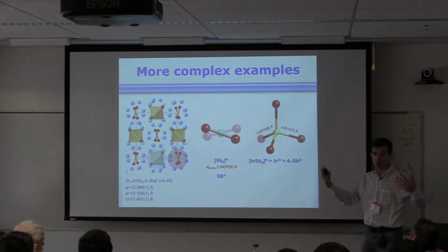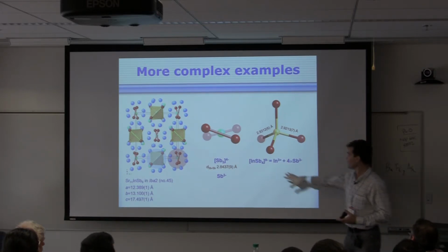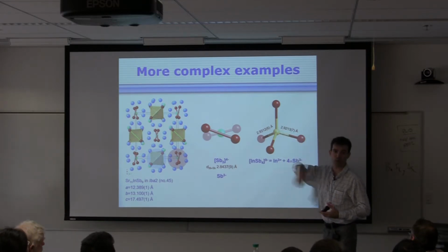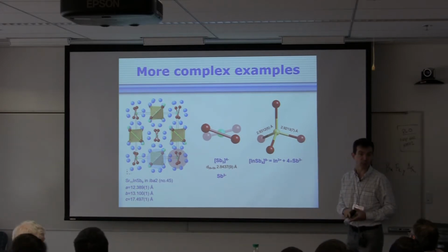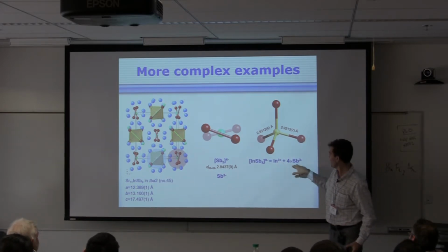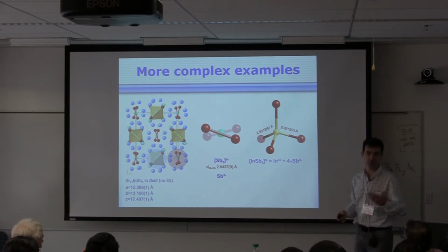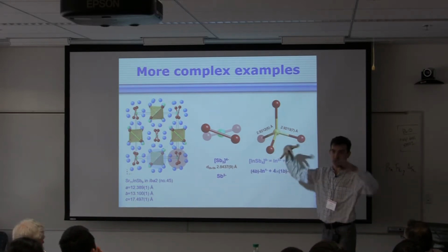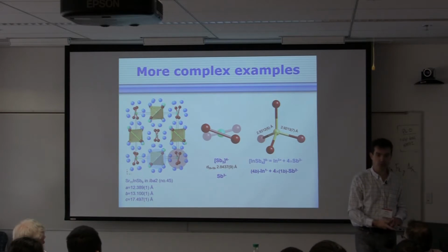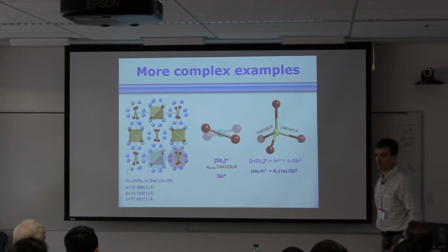But this is a formal way of partitioning electrons. It doesn't mean that this thing exists, or that you can dissolve it in any solvent. It's just bookkeeping of electrons. So indium 3+, each antimony 3-, this becomes 9-. Or I can do something even crazier: indium, a group 13 element, forced into a coordination environment reserved for group 14, has to have a formal charge of 1- to be tetrahedral with 4 bonds.